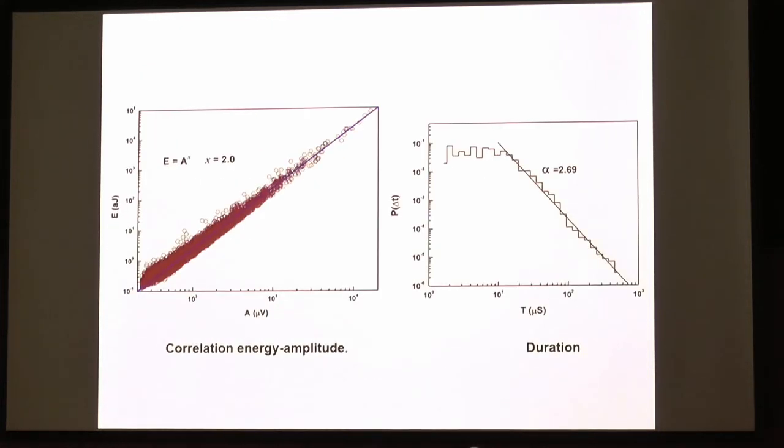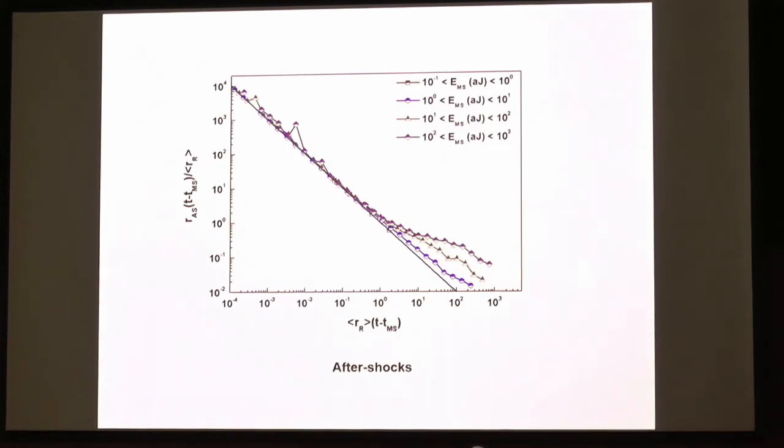So we can do that for various correlations now. We can do that for energy amplitude correlations. We can do that for durations, how long these jerks are taking. And we can do that for the probability of aftershocks. And you can see the log-log is pretty good to a certain point. And the aftershocks follow all the big shocks, then the small shock, which comes with the probability of 1/T.